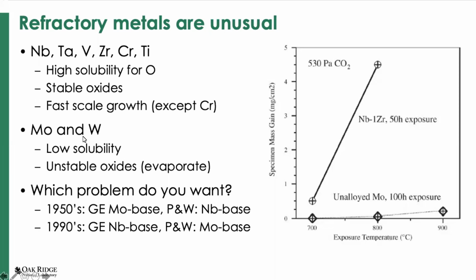The opposite is moly and tungsten, where you have low solubility for oxygen, but relatively unstable oxide. So you have a tendency at high temperature for the oxide to evaporate. And so the question becomes, which problem do you want to address? And so, again, my mentor, Jim DeStefano, got a good laugh out of the fact that when he started in the 1950s, GE was working on moly-based alloys and Pratt & Whitney was working on niobium alloys. And when things reshuffled in the 1990s, they had reversed. And he felt that Pratt & Whitney had learned a few things and chose a different pathway when they had an opportunity.